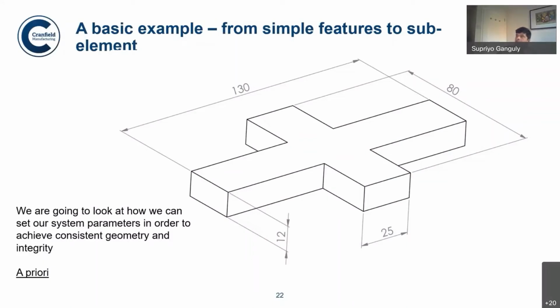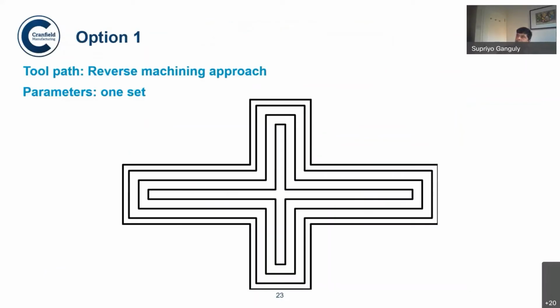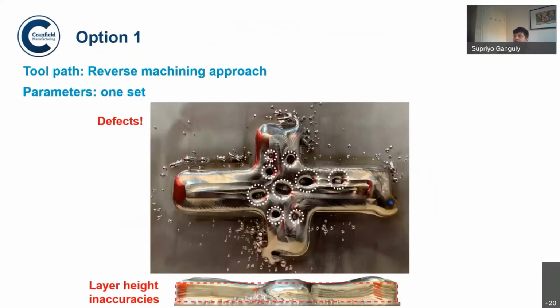So this is option 1. It is just like a reverse tool path approach. So we start building from the middle, and slowly it goes out, and we use the same parameter set and everything. So now you can see the component, which is completely riddled with defects, and the layer height is completely inaccurate. It is because the thermal mass of the depositing mass is continuously changing, and unless these are addressed, it will never be able to generate a structurally sound component.